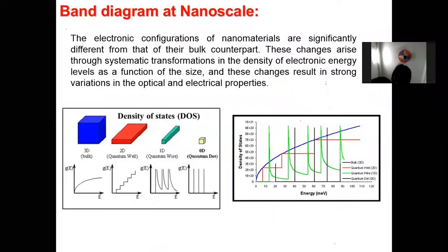If you see the band diagram, I have shown 3-dimension, 2-dimension, 1-dimension, and 0-dimension. You see how the density of states changes with energy. In 3-dimension, it is a beautiful curve, but in 2-dimension, the quantum well starts coming, and in 1-dimension, it breaks up, and in 0-dimension, it is separated. This is what is called quantum confinement. So you have a different band structure for a different material at different dimensions. The energy state changes like this. So you have a quantum confinement effect when you are in nano size. When you are in bulk, you have a fixed band gap. So the band gap changes with size changes in the nanoscale.